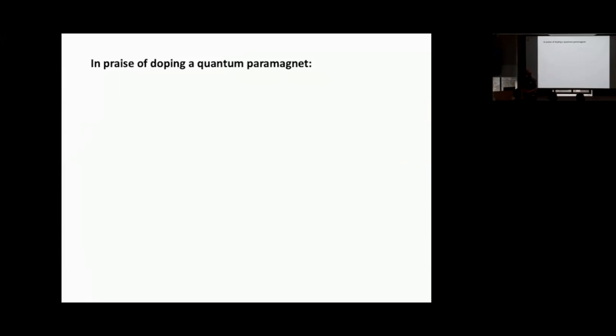I want to go a little bit further on this idea that superconductivity is best when we dope not into an antiferromagnet, but into a quantum paramagnet. And in particular, although the line of reasoning in the first result that I showed you was an RVB result, which envisaged the quantum paramagnet as being a spin liquid, I think it's the quantum paramagnet probably more than the spin liquid which is important. And let me present the evidence for that statement.